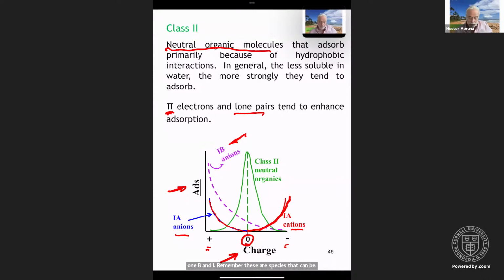So if we look at the species, we notice the dashed purple line, and we notice that at positive charge densities, the amount of stuff is much higher than simple electrostatics. This much difference. Moreover, even when the net charge on the surface is zero, you still have adsorbed stuff. It takes a much more negative charge to completely displace that species. And we can take that difference as a measure of the strength of the interaction. The more strongly adsorbed an anion is, the more negative charge on the surface you'll need to displace that species.